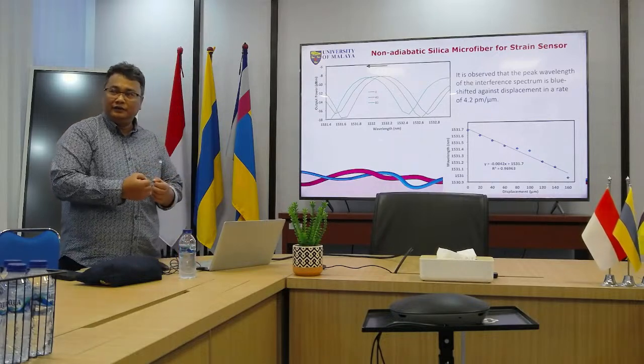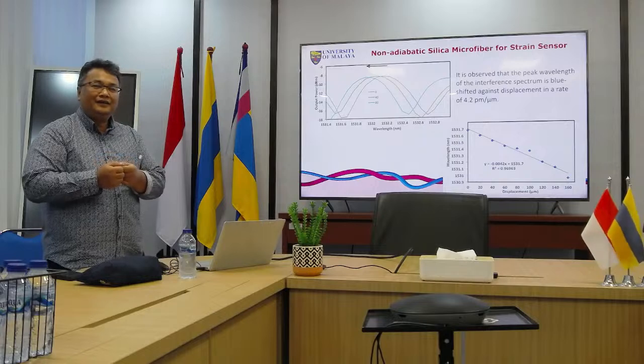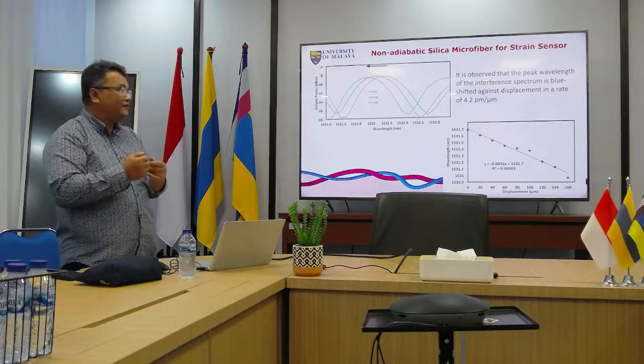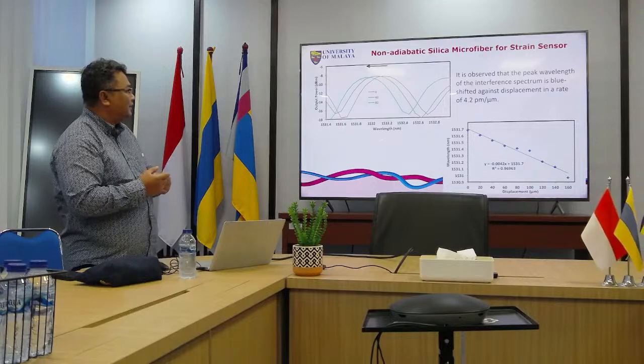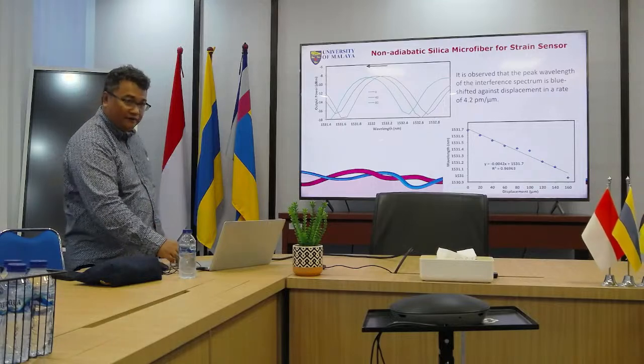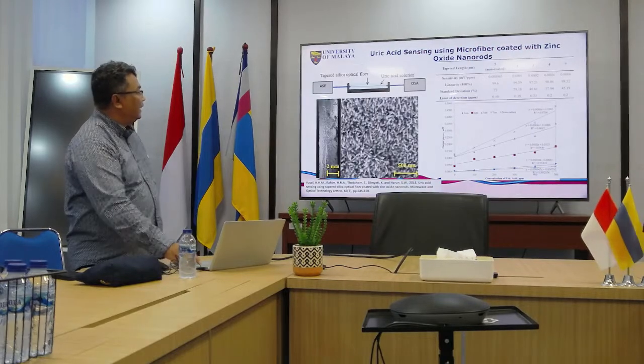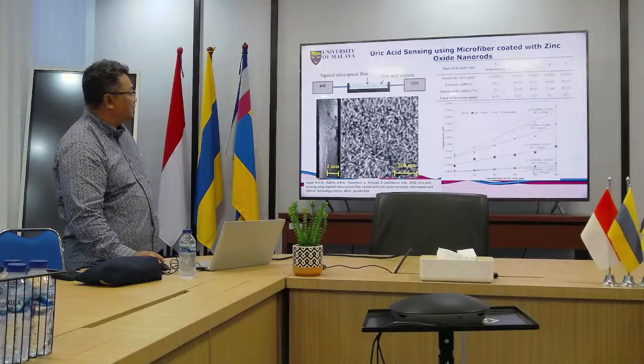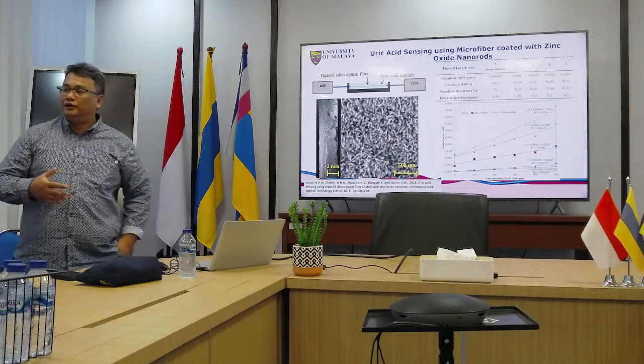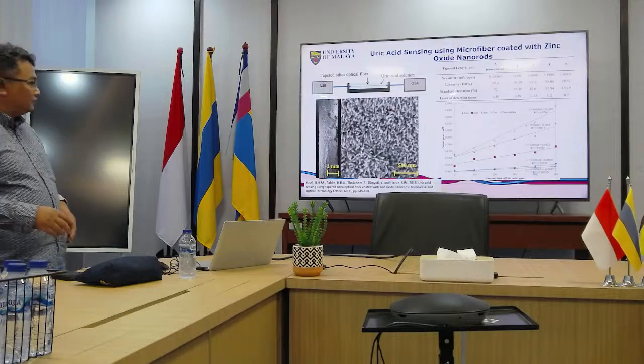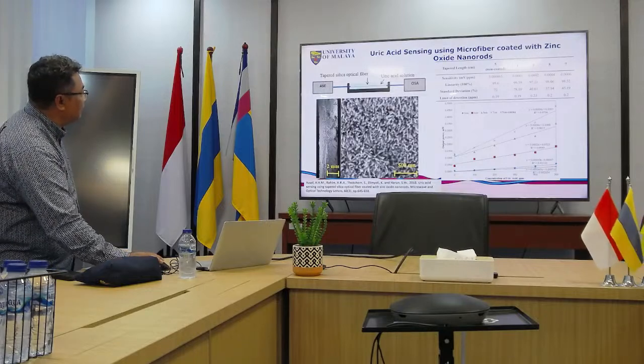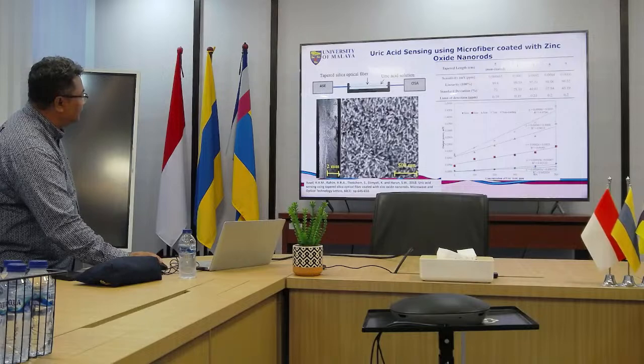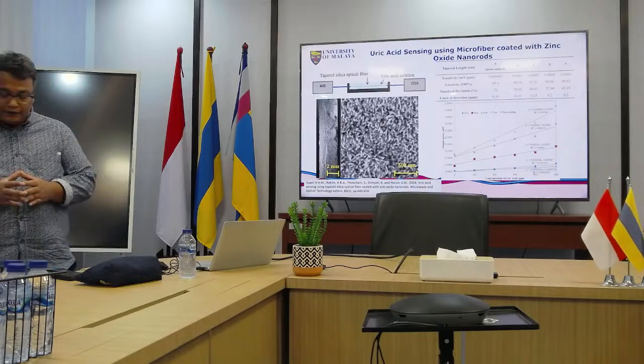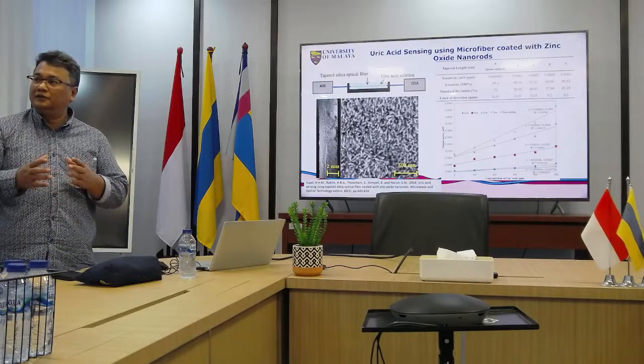Strain sensor, even at small nano size, they are very robust. They're very good for strain measurement. And this we can coat something. This we do with the zinc oxide coating. You can coat the microfiber here, for example, for uric acid sensing. So we coat the microfiber, the fibers. You can put zinc oxide nanorods using the hydrothermal process.